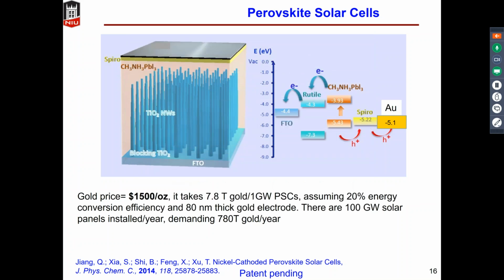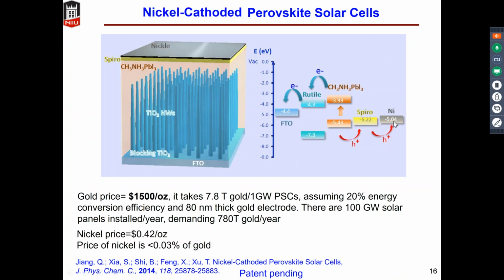So using gold is certainly not a sustainable option for the commercialization of perovskite solar cells. This prompts us to think of some other choice. So we use nickel as the counter electrode. Nickel has a very similar work function as gold, but at a much lower price. So we actually have used nickel as the counter electrode and conducted some research.